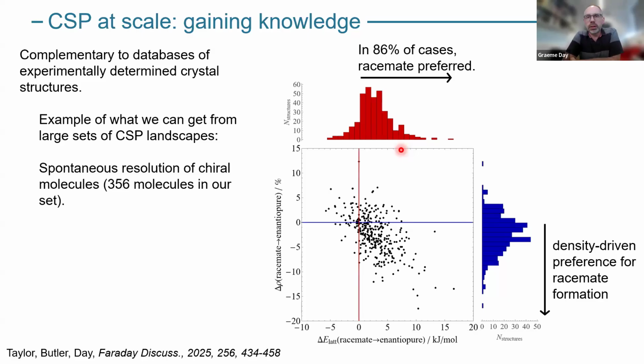One thing we looked at briefly, and we're looking at a bit more closely now, is chiral molecules, where you can have a right-handed and left-handed version, which are non-superimposable. If you crystallize from a solution which is a mixture of those, you have two possible outcomes. Either you crystallize where you have the right and left-handed together in a racemic crystal, or you get separation. Experimentally, it's well known that racemates tend to be preferred. Most chiral molecules will crystallize to a racemate, and I think it's in less than 20% of cases that you get enantiomeric separation. And we can look at this now in our database.